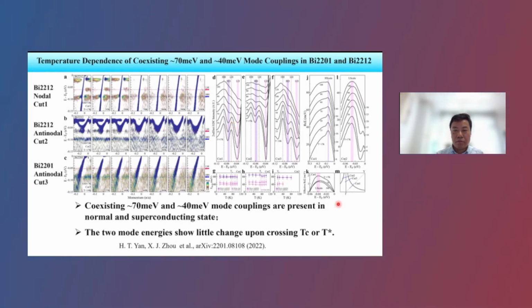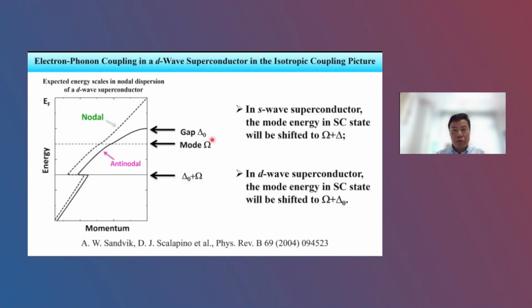Okay, but it is also very interesting to note that this energy scale does not change with temperature. It should change when you cross Tc or T star, but it does not change. This is very unusual because in the conventional picture, when the sample is in the normal state and you have an electron-phonon coupling, the phonon has the energy of Omega, and in the superconducting state, this mode scale should move up to Omega plus Delta.